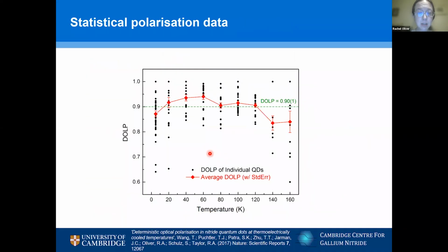Just showing you some statistics of that on this next slide. We can see that the average degree of polarization amongst these dots is about 90%, but within our ability to measure, some of the dots are 100% linearly polarized.